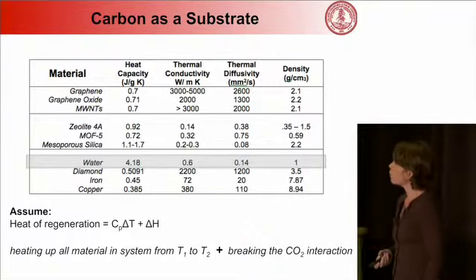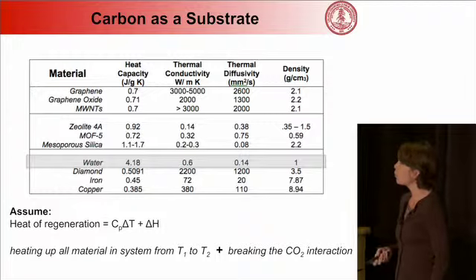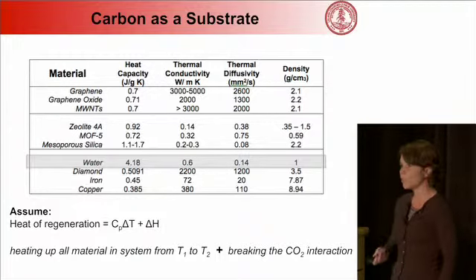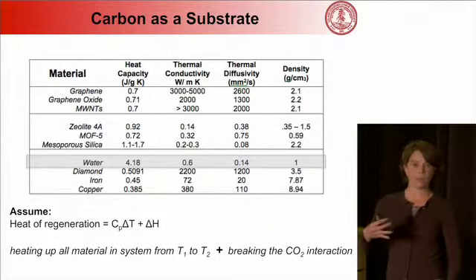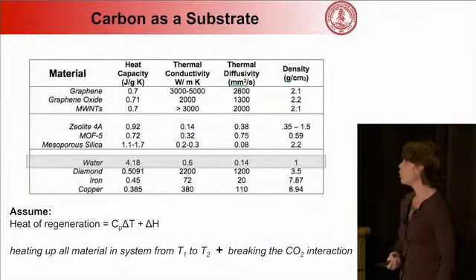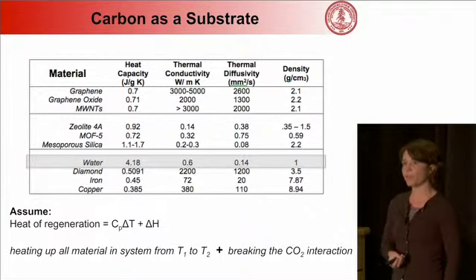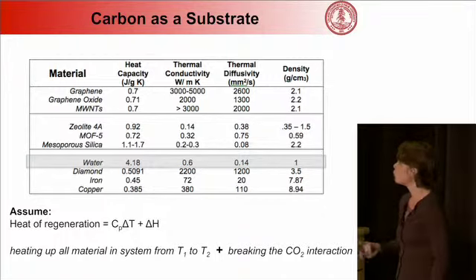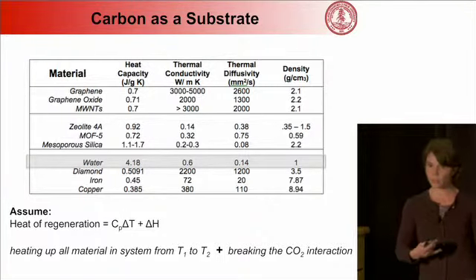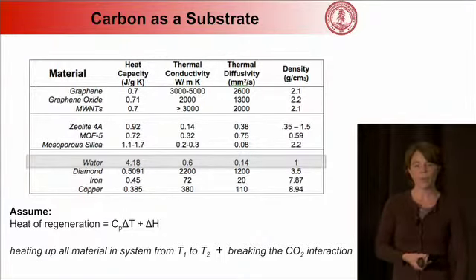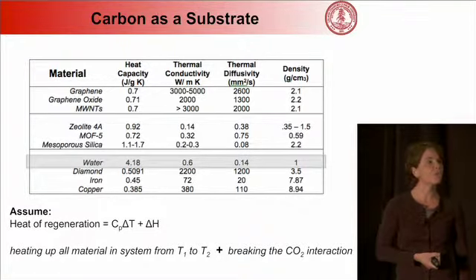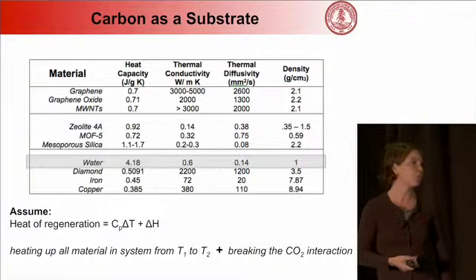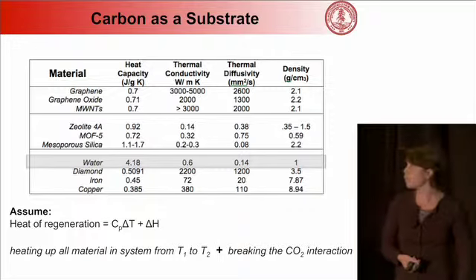So we wanted to look at something that might have a low heat capacity, remembering that the heat of regeneration is equal to the heat capacity multiplied by the temperature change, in addition to the heat of reaction. So the reaction required to bind the CO2, we also have to break that for regeneration. The other aspect is the thermal conductivity associated with carbons is very fast. So if you're thinking about thermal processes for regeneration, you want the heat to be able to move through these materials rapidly. And so these were the properties that we thought about that were important for carbon.